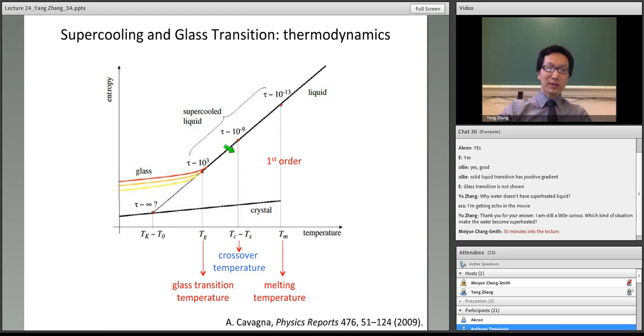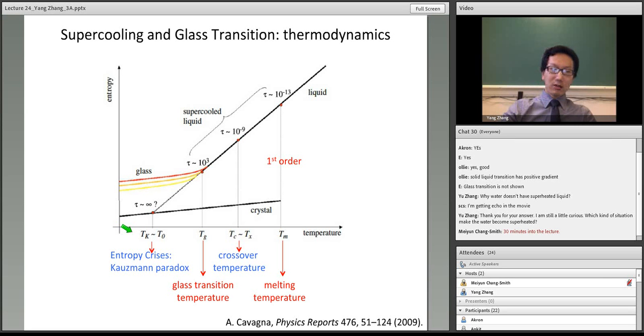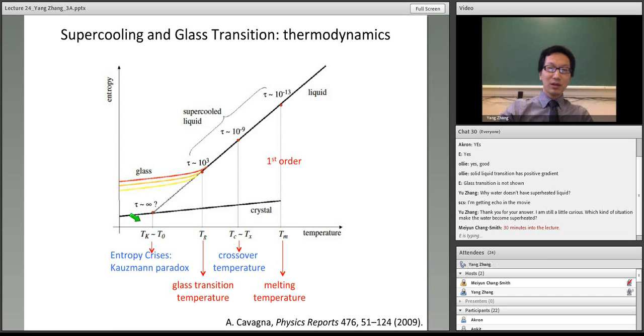The last temperature that I want to mention in this figure is here. This is the so-called Kauzmann temperature. The reason is that when people first studied the entropy of the system in the liquid state, before reaching the glass, we could extrapolate this line. If the glass transition doesn't happen, the entropy should keep going and eventually hit the crystal. And if you go below the so-called Kauzmann temperature, the entropy of the glassy state would be lower than that of the crystal, which is against our common belief. We always believe that the crystal has the lowest entropy, so the crystal is always the ground state.